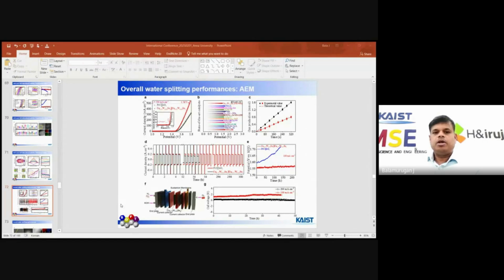We made full cell devices like AEM, anion exchange membrane water electrolysis. When going for acidic media, we have to use PEM, proton exchange membrane. But here it is anion exchange water electrolysis, and we did the stability test at 200 and even 500, almost maintained. But in the case of 600, a little oxidation happens, but not much. So we claim that this catalyst is one of the best catalysts for both OER and HER.